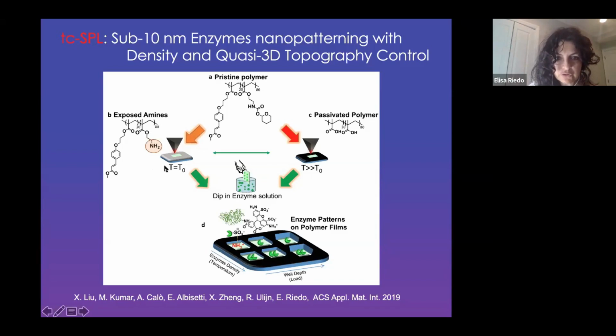Then, as I said before, you can either expose amine groups at a certain temperature and then dip in an enzyme solution, or, as we realized, if heating at a much higher temperature, you can go through a different chemical path and passivate the polymer. So depending on the temperature, you can change the amount of amine exposed. You can decide to passivate the polymer, and this is by controlling the temperature, okay? Like I said before, the gradient, right? The temperature can control the density of how many amine groups we can expose.